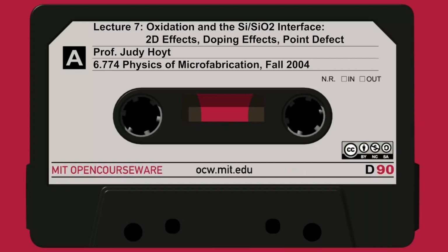So we're going to take this structure now, put it in the furnace at 1,000 degrees in moisture or water vapor for quite a few minutes and see what happens as we oxidize it. So here on the left on slide 18 is the starting structure, and now look, after 450 minutes of oxidation, this is the simulation.